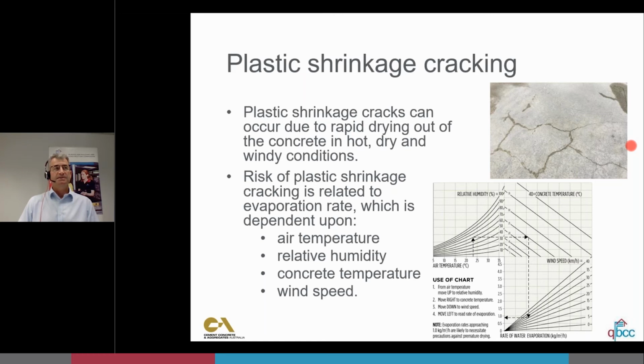There's times where plastic cracking is a higher risk, and that's hot, dry, and windy conditions. And there's a little diagram here that allows you to work out what the evaporation rate is going to be depending on the relative humidity, the concrete temperature, and the wind speed. Or you can just use the CCAA app that'll look at the weather conditions and tell you. And if you get evaporation rates up around 0.8 or 0.9 kilograms per square meter per hour, it's high risk of plastic cracking.